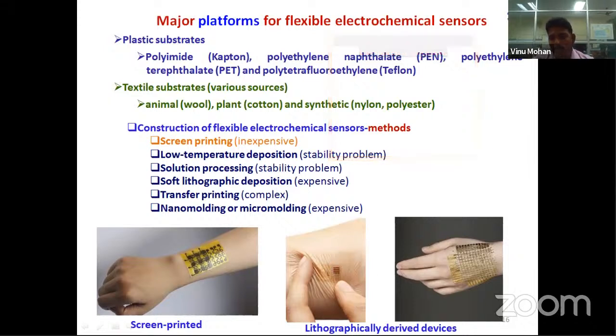So these are some of the examples of screen printed electrodes, and these are some of the lithographically derived devices. One advantage of lithographic devices is that we can have extremely thin coatings, and we can control the resolution to even micron size or less than micron size. But if we consider screen printed, it is like 50 or 100 micron size; only above 50 or 100 microns can we have the electrochemical sensors. This schematic explains how we can prepare screen printed electrochemical sensors.